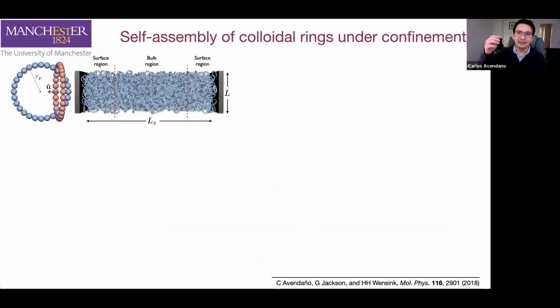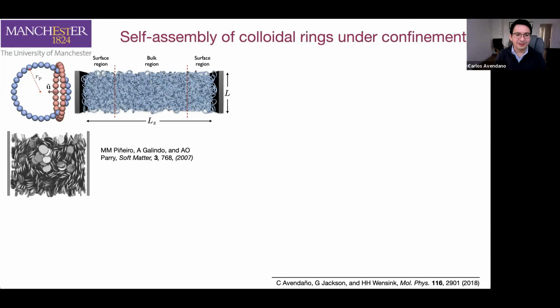What you will imagine is that the ring will try to lie completely flat to the wall. It makes absolute sense that that should happen. And we were expecting to observe something similar, those rings would start adsorbing to the surface completely flat, similar to this paper by Amparo Galindo, where you can see the particles adsorbing flat next to the surface. But what we observed was something completely different.